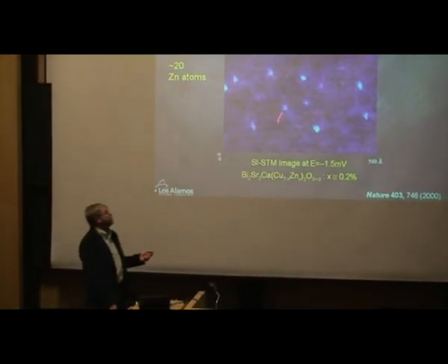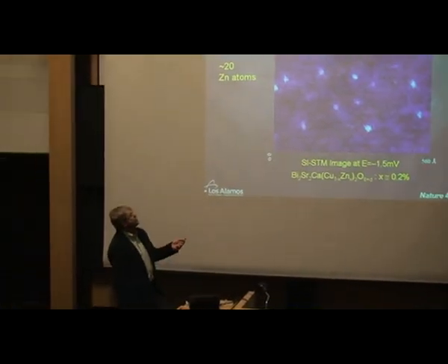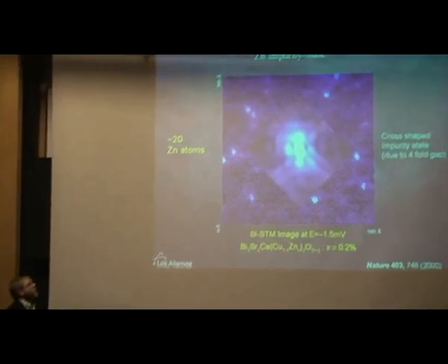And they were observed. This is actually the resonance seen on the impurity site, specifically the zinc site, in the bismuth 2212. So this is not exactly this nanoscale inhomogeneity. This is deliberately placed, assuming things are under control, deliberately placed defects into this material. So those are the impurity sites. Those little cross-shaped states. That's how they look if you zoom in.